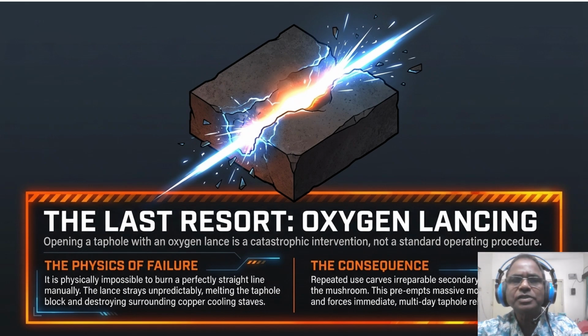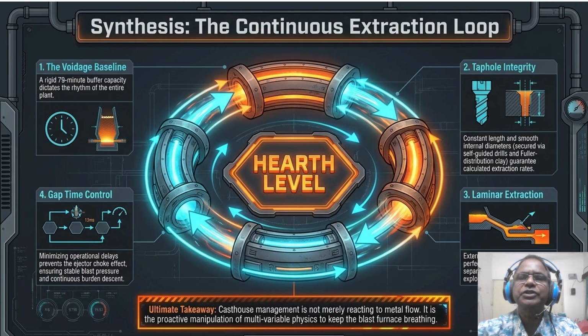So to avoid the lance, we must close the loop on all the physics we have discussed. So we conclude with the continuous extraction loop. It starts with a voidage balance, a 79-minute buffer that dictates the rhythm of the entire plant. Second, we maintain the taphole integrity through precision drilling and high performance clay. Third, we ensure laminar extraction by managing trough geometry and the 10 centimeter rule. So finally, we exercise gap time control to prevent the ejector choke effect.